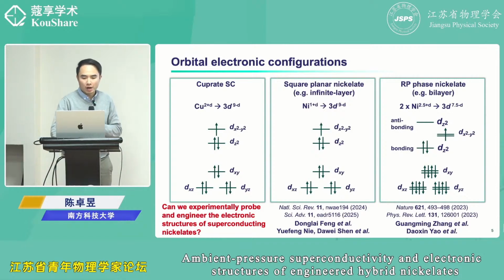But for RP phase, Ruddlesden-Popper phase nickelates is very different. Take this bilayer as an example. Because of the existence of the apical oxygen, the two nickel oxide planes are coupled so intimately. So you need to consider both planes together, and so you can see these states are doubled. The number of these states are doubled.